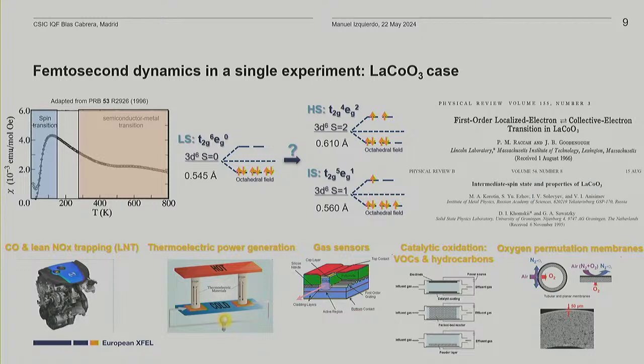So I'm going to present one example from my own research, and this is the case of lanthanum cobalt oxide. This is a 3D perovskite, and this compound has been investigated for more than 50 years based on the fact that there is a low temperature spin transition around 100 Kelvin, and the system also has a semiconductor to metal transition that goes very smoothly from room temperature up to around 600 Kelvin. So the debate is what is the excited state of the system.